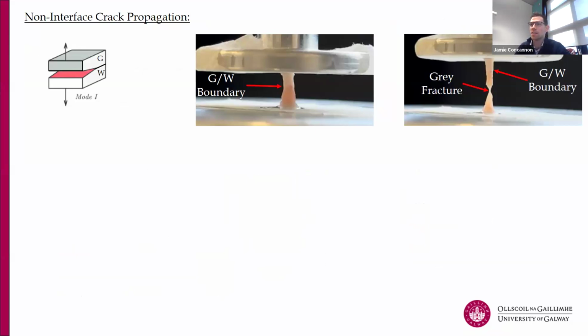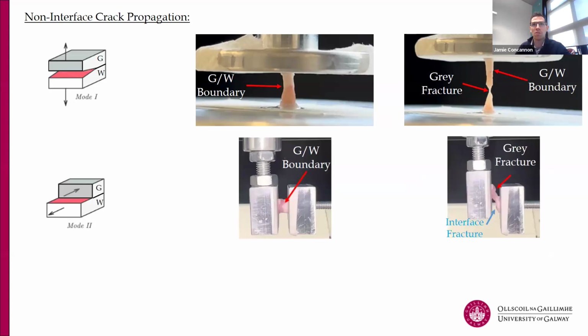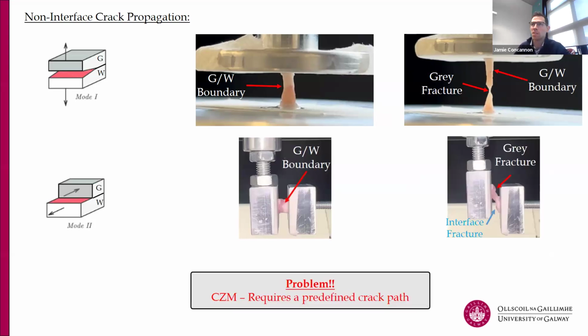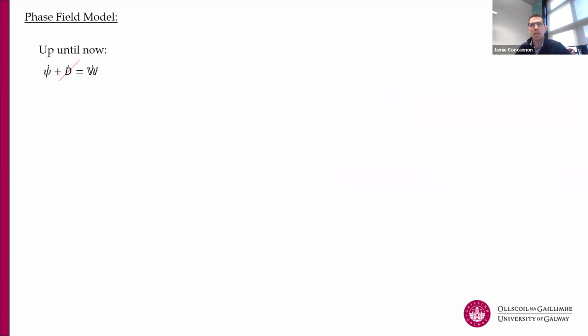So the brain tissue is easier to break, or a crack to form, in the bulk tissue than at the boundary. Not in all cases, but in a significant number of cases in both mode 1 and mode 2. And this is where our problem came, in that the cohesive zone model requires a predefined fracture path or a crack path. So let's go back to our drawing board and back to our computational model, and we had to add back in that dissipative term.